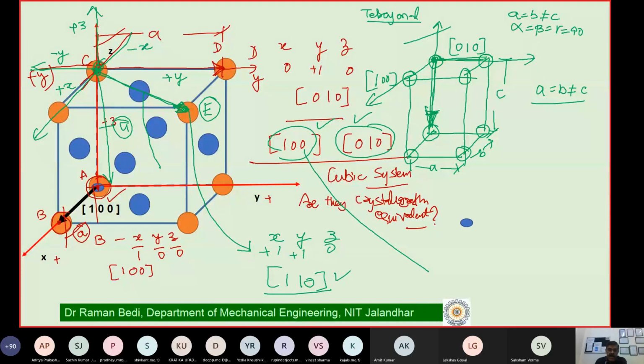No, sir. In a cubic system, no, it is not, because here the interatomic spacing is not A. If it is simple cubic, you have a lattice point at root 2 A. If it is FCC, just like it's shown here, you have something in between also, root 2 A by 2. So in both cases, whether FCC or simple cubic, 110 is not equivalent to 100. Understand? Yes, sir. Okay. Let's move forward from here.